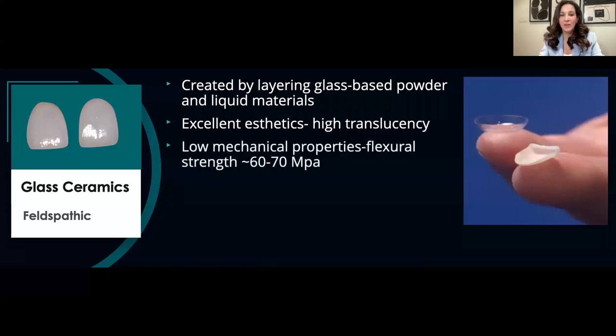However, as I mentioned before in the graph that you saw earlier, it's got very low mechanical properties. The flexural strength is only between 60 to 70 megapascals. And so how can we use this in clinical practice? And the reason we can use it is that the strength of this material is derived by bonding onto enamel.